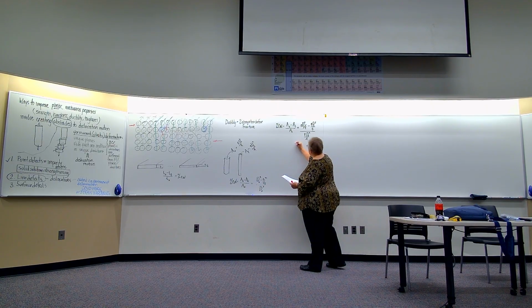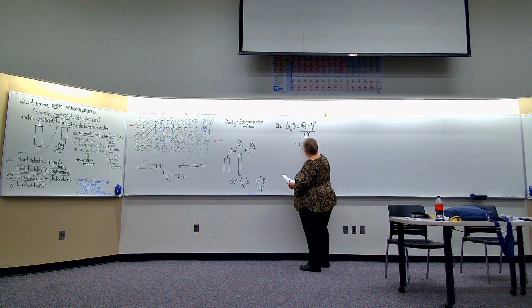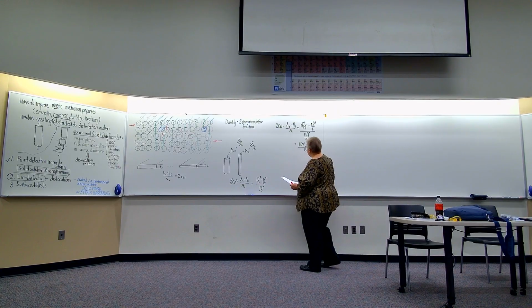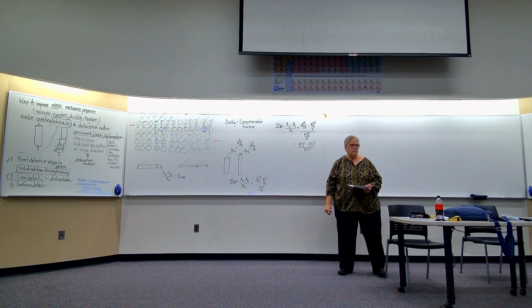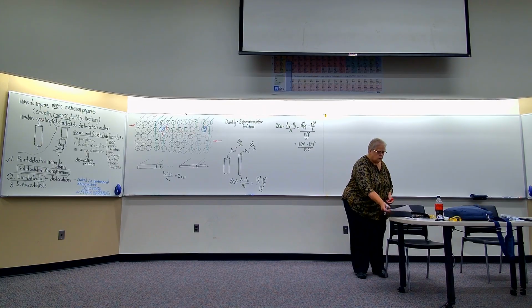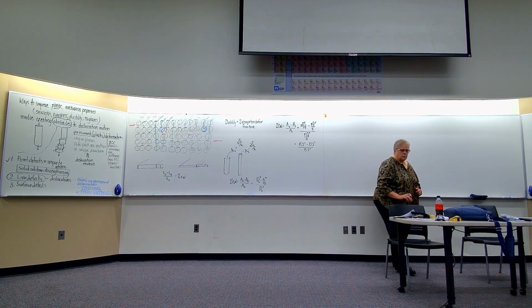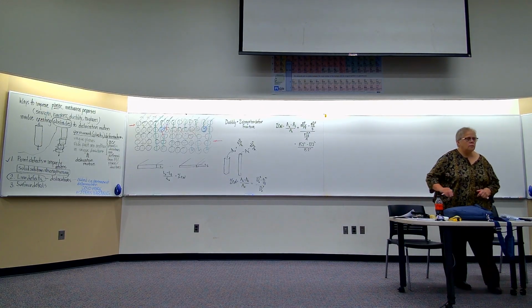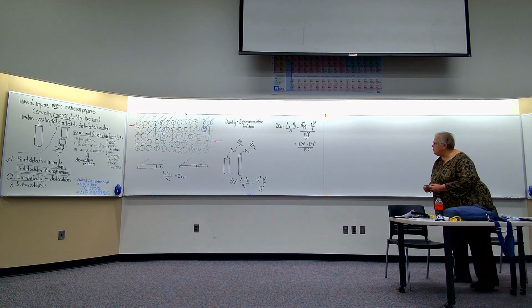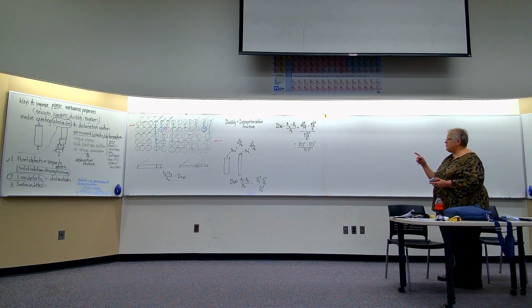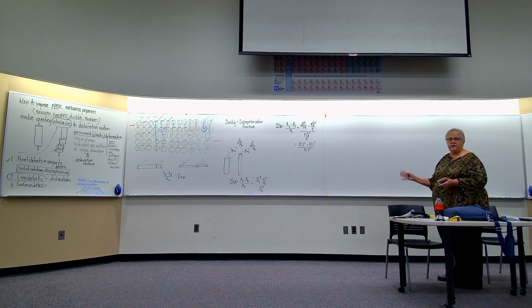And I have the original diameter 15.2 squared minus 12.2 squared, divided by 15.2 squared. Now, this isn't the same as 15.2 minus 12.2 quantity squared, you know that.